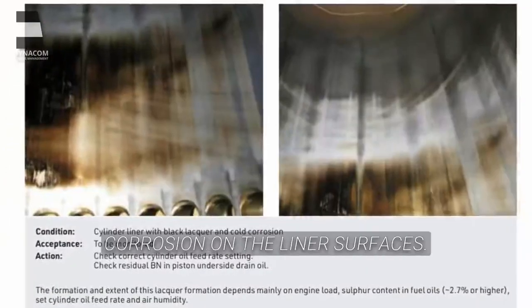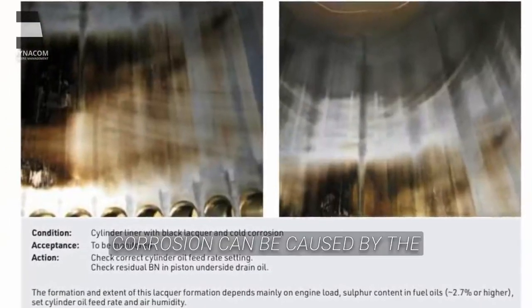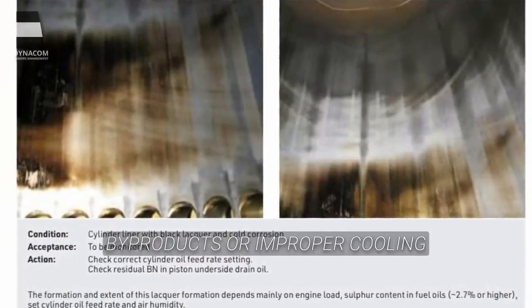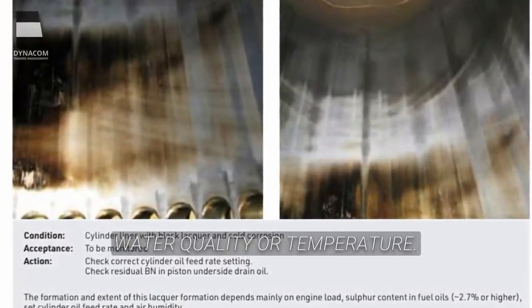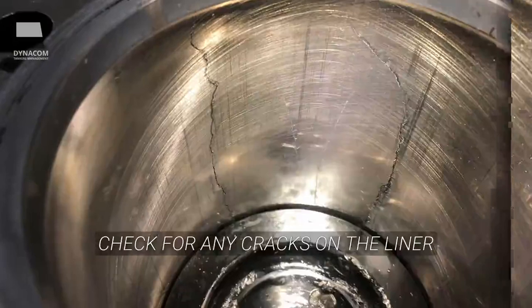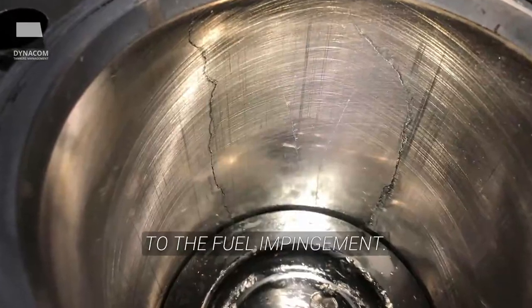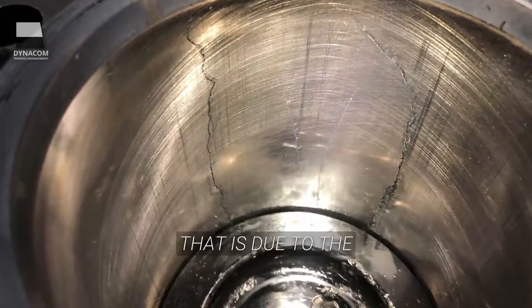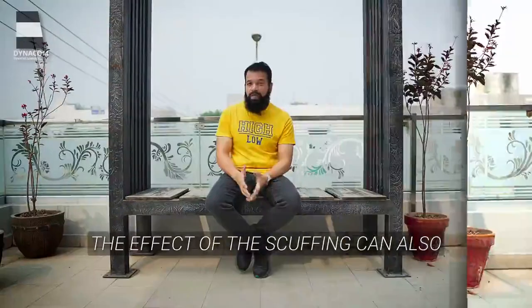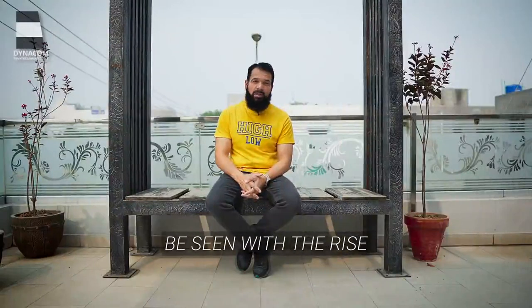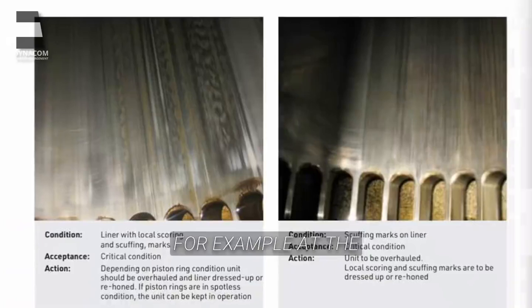Check for signs of corrosion on the liner surfaces. Corrosion can be caused by the ingress of acidic combustion byproducts or improper cooling water quality or temperature. Check for any cracks on the liner wall, which may be due to fuel impingement, that is, due to a defective fuel injector. The effect of the scuffing can also be seen with the rise in surface temperatures, for example, at the cylinder liner wall.